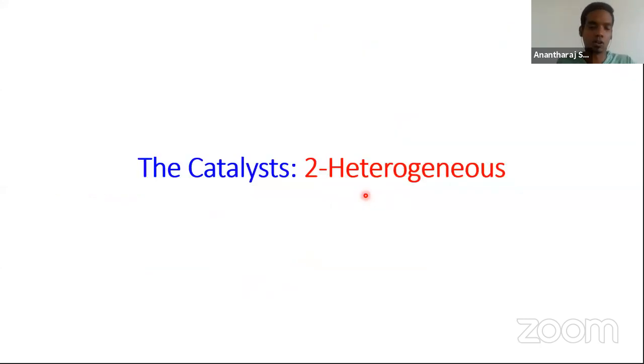Now let's move on to heterogeneous electrocatalysis. As I introduced earlier, heterogeneous electrocatalysis is where we do water splitting by fixing, or I can say immobilizing, the electrocatalytic material on a particular substrate electrode, where we apply potential directly by making electrical contact. This is advantageous when compared to homogeneous electrocatalysis, because there we did not have direct electrical contact with the catalysts dispersed in solution. So we needed to depend on a large amount of supporting electrolyte concentration. But in this case, we just avoid this difficulty. That's why these are able to give us several advantages, I mean, high activity, low over potential, long-term stability, and many other things.